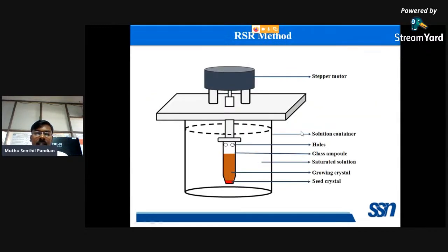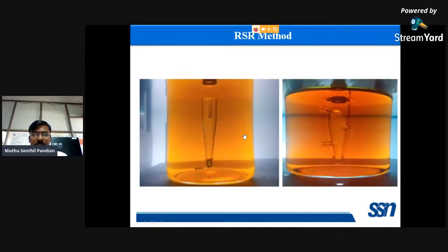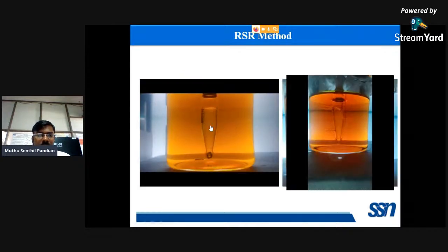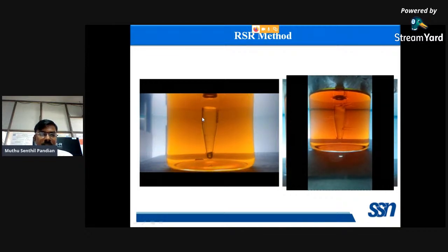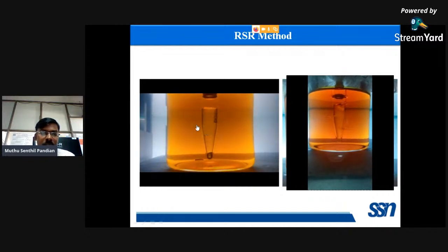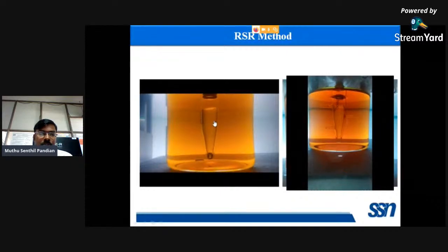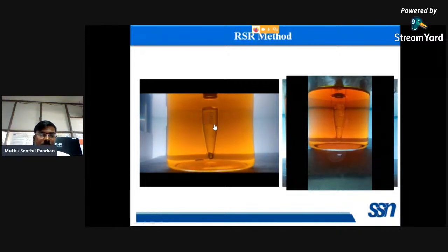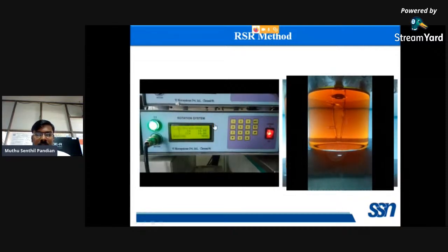So in order to avoid this impurities accumulation, we have made a small hole like this. Several slabs we have made in the SR glass sample, and we have grown the crystal like this. So here the impurities are filtered from the glass sample. So the impurities can be controlled in the RSR method compared with the SR.